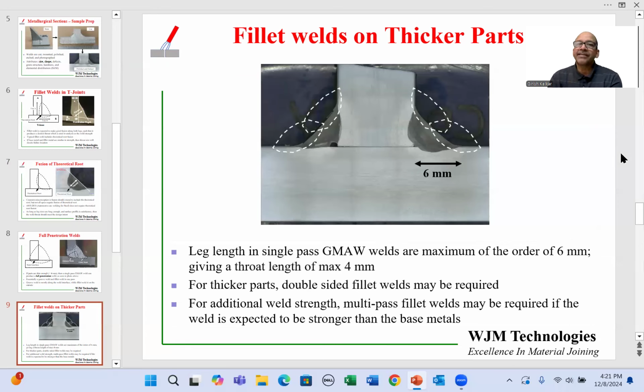Now if the design engineer wants to make a weld which is as strong or perhaps stronger than the base materials, then the design engineer may have to specify two welds, one fillet on one side and one on the other side, but that still gives us about 8 millimeters. So 4 millimeters of throat here, 4 over here, that's 8 millimeters. And if you're talking about shear failure, and the base metal itself is more than 8, then again the welds will be the weak point. If you want welds to be stronger than the base material, then the design engineer may have to specify a larger leg length, and that can only be achieved by multiple passes, as I've shown in the schematic over here.